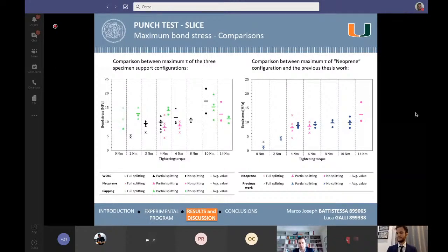While on this graph, we can see the data achieved with the neoprene configuration, again compared with the one of the previous thesis work. Here, the two configurations are very similar. In fact, both of them had a neoprene layer, and that allowed us to reduce as much as possible the variables of the test. We can see that for lower tightening torque, in both cases, these configurations are not suitable to avoid the concrete splitting, while for higher tightening torque, the results seem similar to each other.